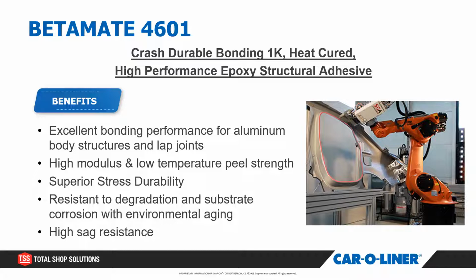So, when I wanted to talk about the adhesives that I worked with at Tesla, the adhesive that was used in the factory was Betamate 4601. This is a Dow product. It's an extremely crash durable adhesive, heat cured, and works great with aluminum. It has high modulus and low temperature peel strength, and I'll get into more about what those categories mean. But it has superior stress durability and it resists degradation over time with environmental aging.